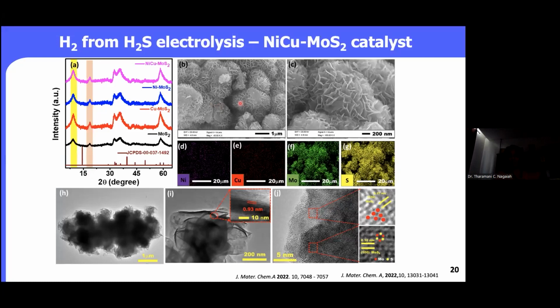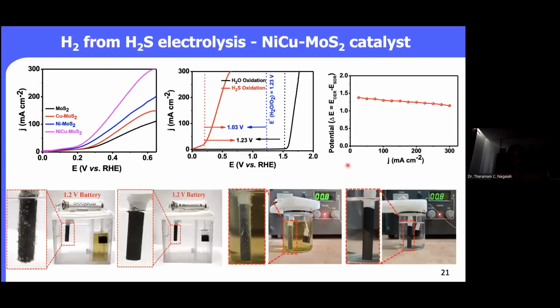And the morphology demonstrates that this is a flower-like structure, and also the TEM demonstrates that this flower-like structure has been modified, the nano sheets. And again, the HRTEM confirms the presence of the 100 plane of the 1T and also the 2H plane of the molybdenum sulfide. That means the presence of two mixed phases and also the uniform distribution and the coexistence of all the expected elements in the synthesized catalyst.